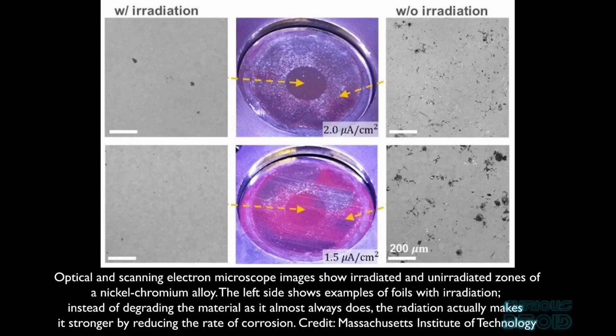Although the research has to be verified by other research teams, they discovered that the proportion of chromium, which is salt-soluble, to nickel, and the amount of radiation could make a significant difference to the corrosion that occurred, and knowing this, new materials could be formulated that will be much more corrosion resistant and eliminating one of the biggest obstacles to molten salt reactors.